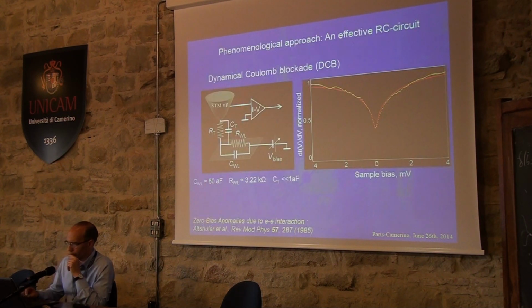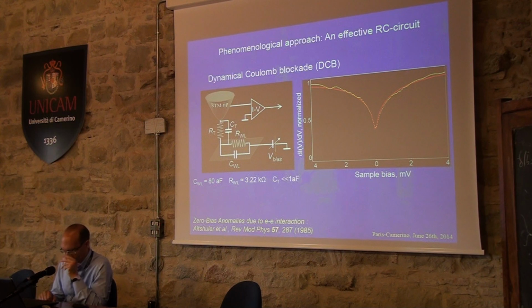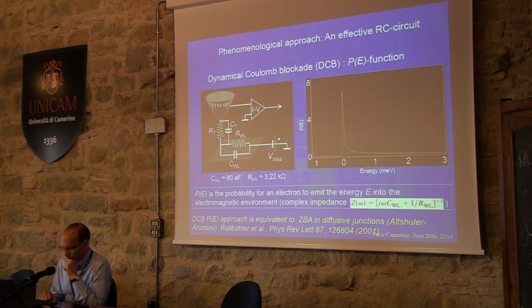So we accounted for this correlation effect by modeling this disordered layer as a network of resistances and capacitances. In this way, we were able to fit the zero bias anomaly with a single effective resistance and single effective capacitance. Introducing this, we implemented the so-called P(E) function. I cannot stop too much to discuss this.